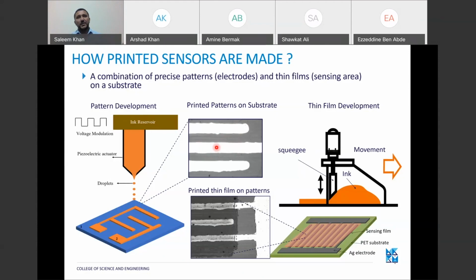Here in this case, we can see there is a bit of variation, but still they are in acceptable ranges, negligible, a few nanometers to a few micrometers. And here in the second slide, you can see we can have multiple structures, not only a single layer. Here, this is the first layer that we have printed in silver, and for the second layer, we can use even the same technology or a complementary technology for thin film deposition, to deposit the sensing layer.